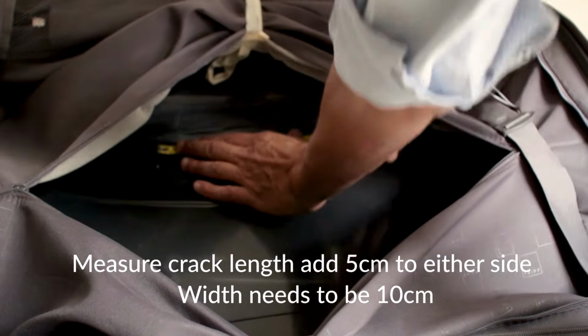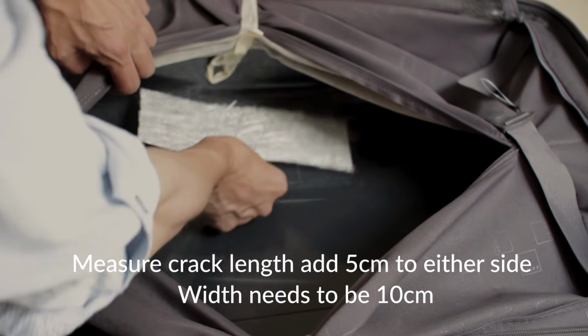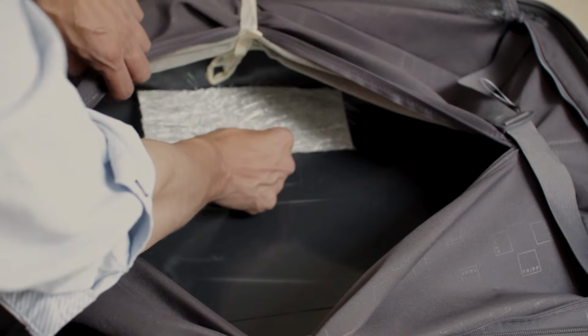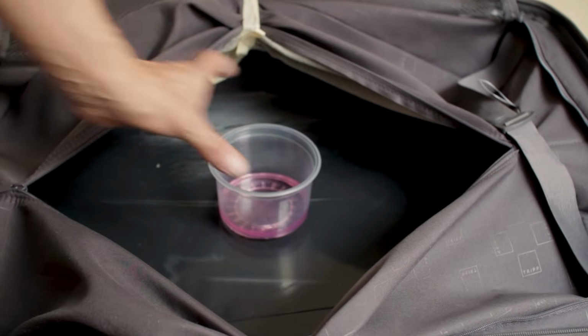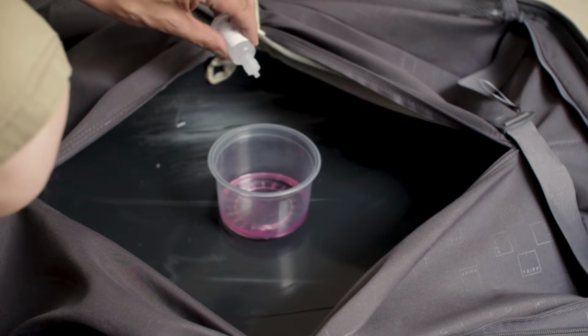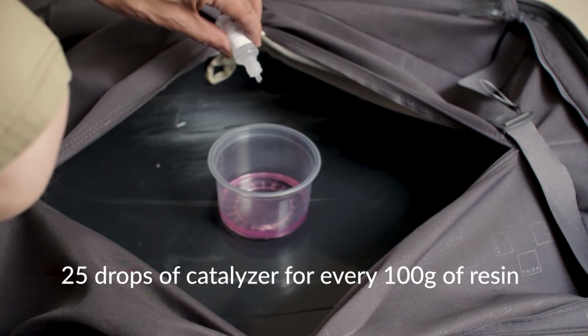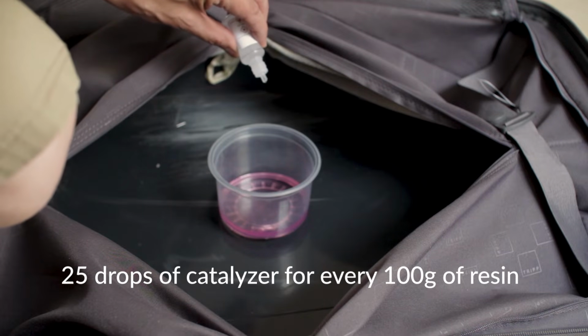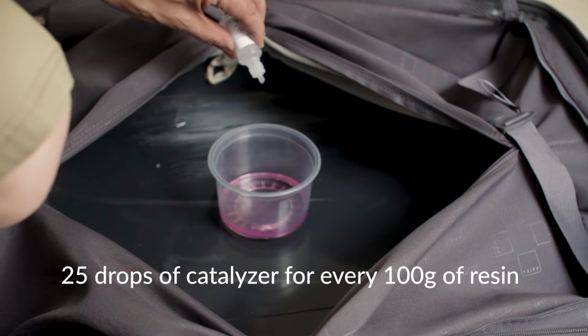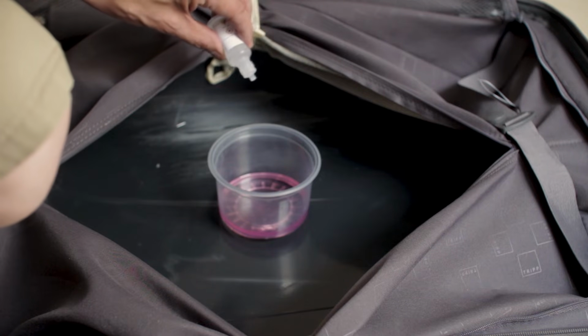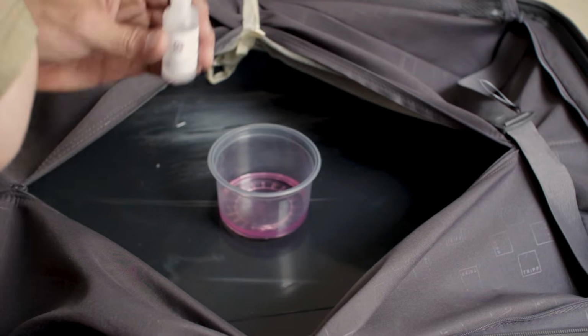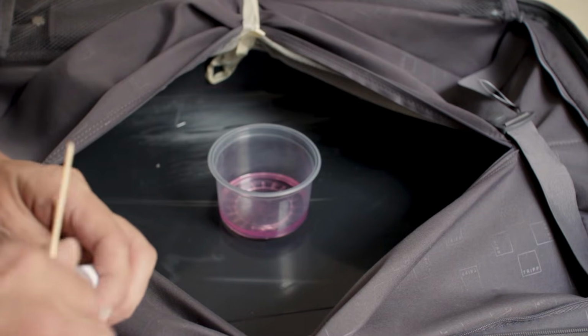It's 4 inches wide, and I need to add 2 inches to either side, so that's 8 inches in total, plus the width, which is 4 inches. I'm using standard fiberglass resin. This particular make requires 25 drops of catalyzer to every 3.5 fluid ounces of resin. When you're using fiberglass resin, make sure you're in a well ventilated room, or better still, outside in the shade.